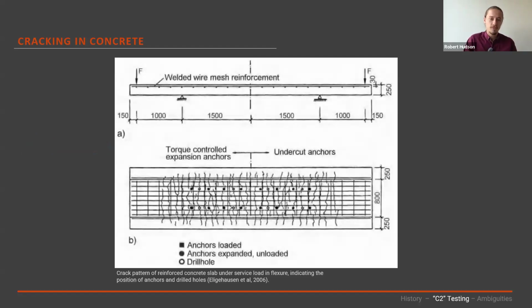Now, taking a step back for just a second, there are two things we really care about with anchors in seismic locations in concrete. We care about the actions on the anchor, which is the cyclic tension and cyclic shear behavior. And then there's the behavior of the concrete, and more explicitly, the cracking behavior of the concrete. Quite intuitively, if we start having cracks in our concrete and our anchors are in those cracks, that's going to impact the performance of any post-installed anchor. Take the extreme case where your crack becomes wider than your anchor and it falls out of the hole. Thankfully, we don't often have that scenario, but it's a spectrum, and the larger the crack, the more impact we have.